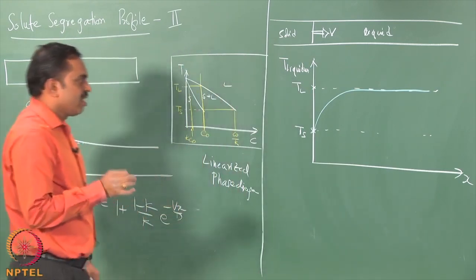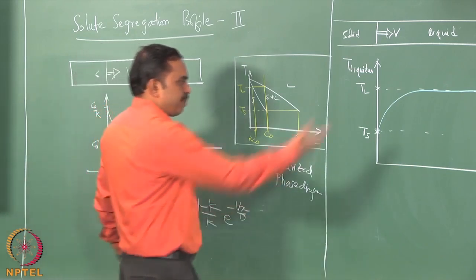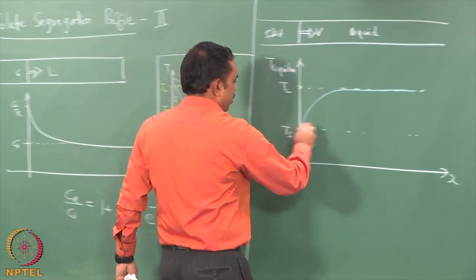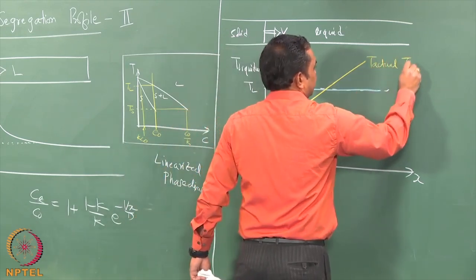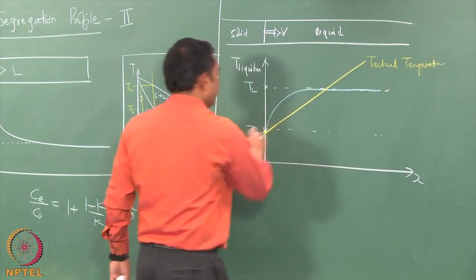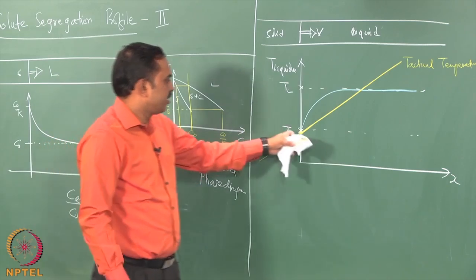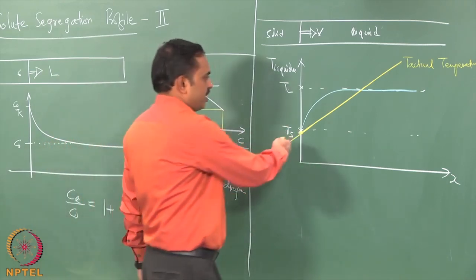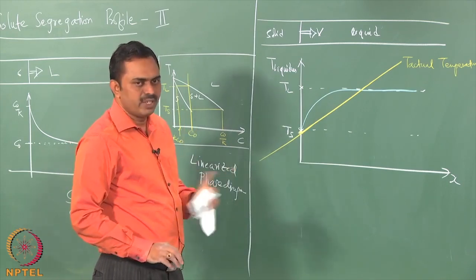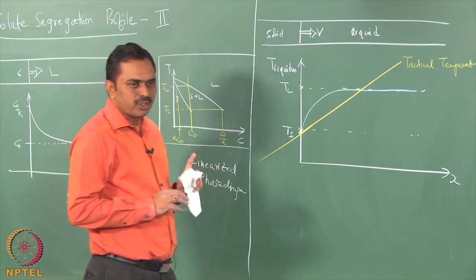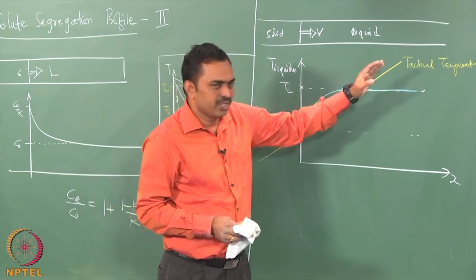This is how the temperature at which the liquid would start solidifying looks. The actual temperature should then be given by a separate plot, going through the same point at the interface where equilibrium conditions for solid and liquid are met. The temperature profile is drawn as a straight line because thermal diffusivity is about four orders of magnitude higher than the solute diffusivity, so the temperature profile evens out much earlier than the solute segregation profile.